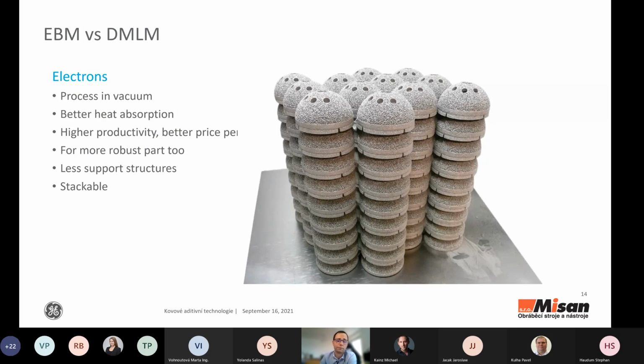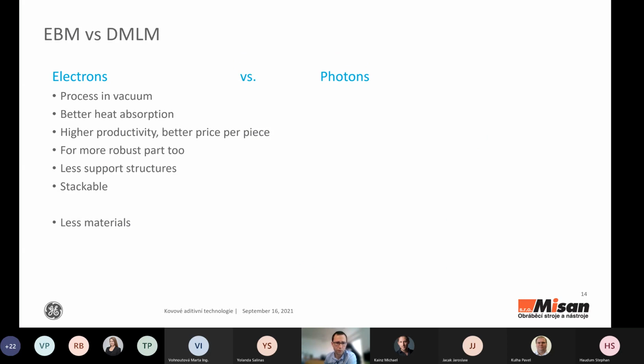Here you can also see the powder cake is blasted away, but it's still stuck together. But you can crack it away. We have fewer materials, but that's usually just because of the typical applications. So with EBM, we don't really have any aluminum or steel because it doesn't really make sense to produce parts from these materials.